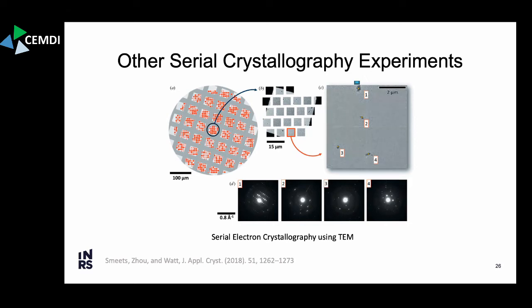And you take low resolution images first, and then you start to identify regions of interest in these low resolution images. And you go back and you focus your beam and you zoom in on a given crystal, and then position your beam there with the deflectors and collect a series of diffraction patterns from different crystals. And this is important. This could be interesting for samples which have more of a beam sensitivity or a dose limit of what they can really tolerate in electron microscopy.